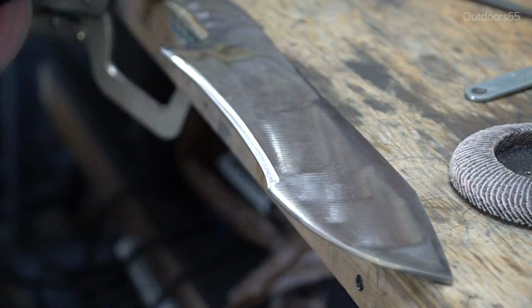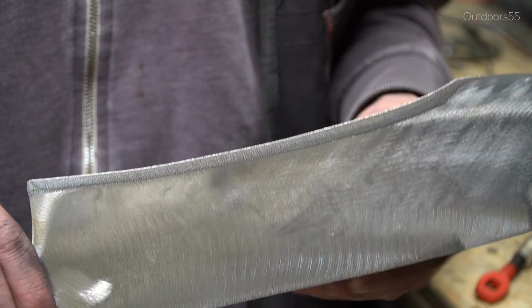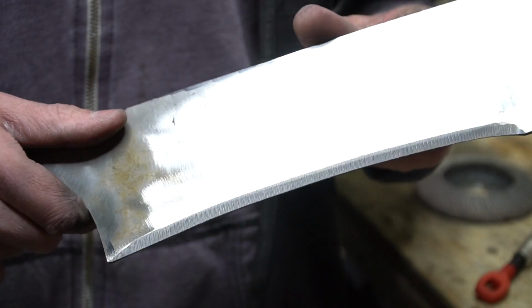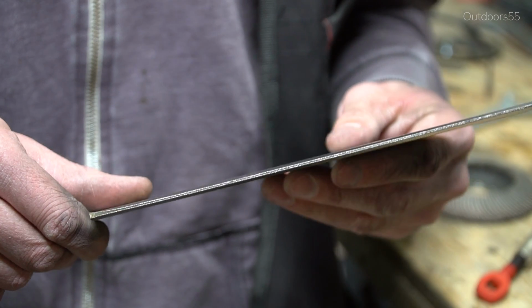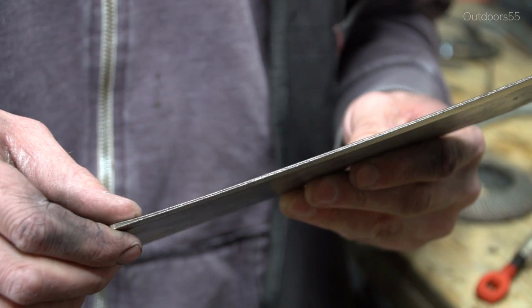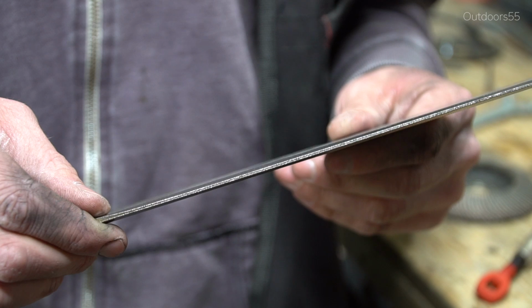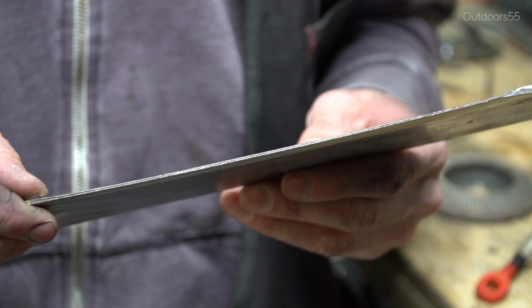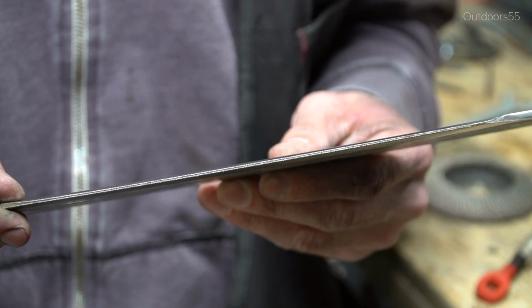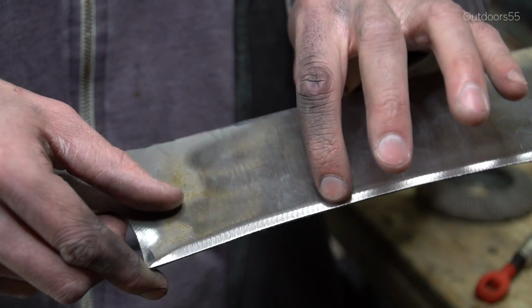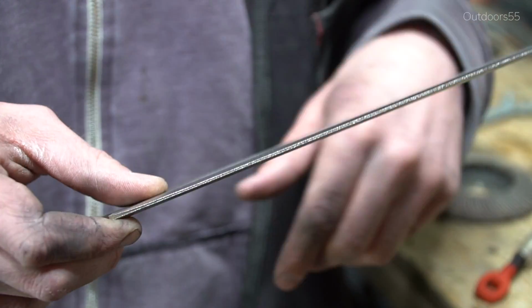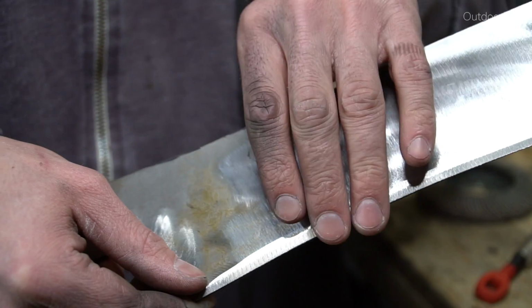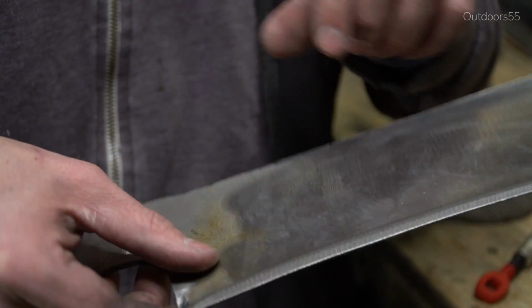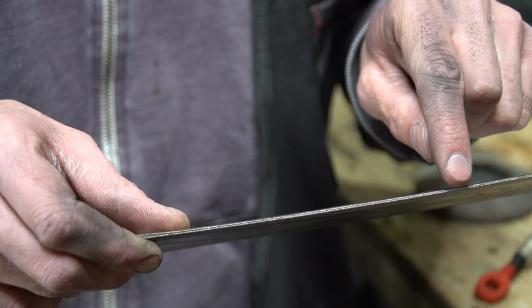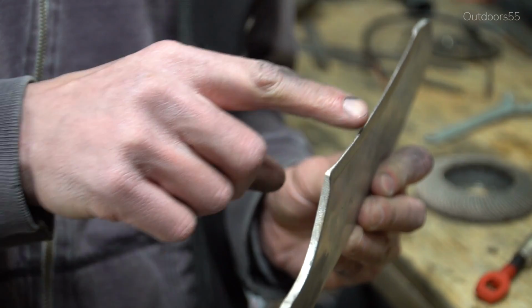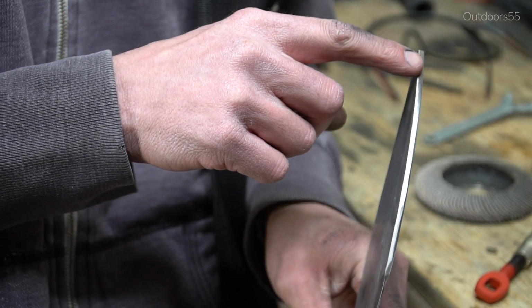Alright guys, so basically what we've done is we started to grind our bevels, and we've ground off a little bit on each side, and we've brought this to about a dime's thickness right in the center. That might not be quite a dime's thickness, but it's close, and it's about even all the way down the entire bevel. The reason that we grind both sides to the center point first is so that we can go back and feather this bevel all the way out, and we don't have to mess with the center line of the knife, and that helps us keep the bevel right in line all the way down to the very point.